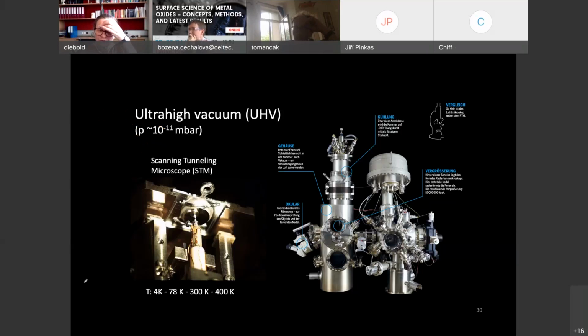Everything we do, we use single crystals. So this would be a metal single crystal, a platinum single crystal, mirror polished to a very shiny surface. And we like to use, and that will be the next part, scanning tunneling microscopy. If you look through this optical microscope on an ultrahigh vacuum chamber, you look inside, you will see the sample on a sample holder. This is about 5 millimeters in diameter. Here is the tip, the very end of the scanning tunneling microscopy tip, a fine needle, and it's mirror polished, so you see the mirror image.